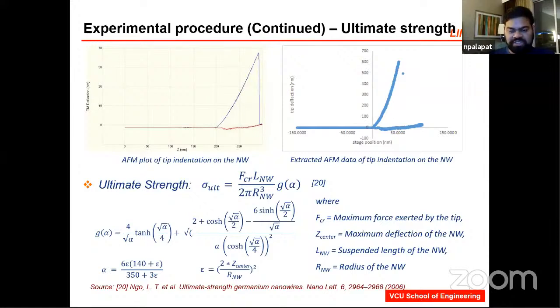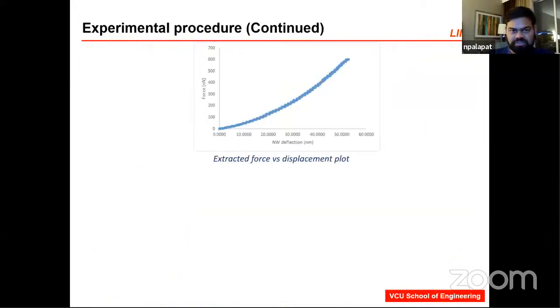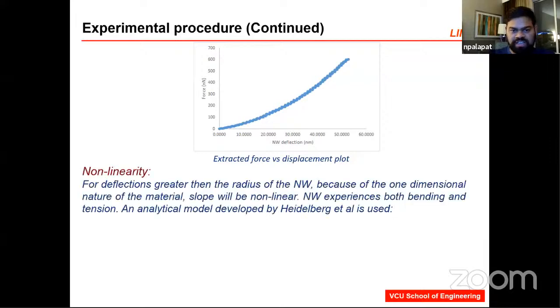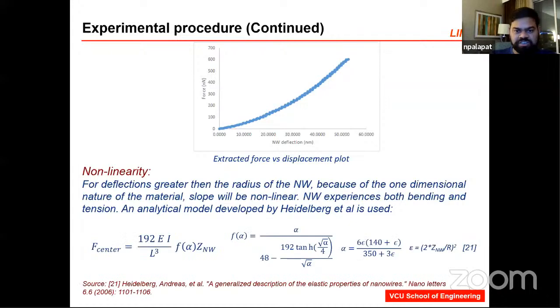Now Young's modulus and ultimate strength are really easy in terms of how the calculation is performed. But the third scenario is where I talked about how you know if a nanowire is sagging, or your AFM tip is causing the nanowire to bend in a different direction. All these nanowires, because they are really small, experience something called non-linearity. Now the model itself is established as an analytical model in your bending and tension models. However, to measure it requires a little effort on the force displacement curves. So here I will show a couple of examples of how this measurement is done.